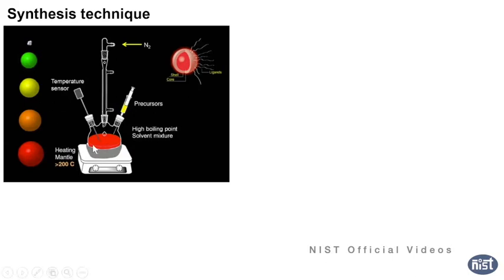And there's a temperature sensor, so you can change the temperature in the solution. Generally we work at high temperature, mainly above 200 degrees, depending on which quantum dot you are making. So you can control the temperature sensor and fix the temperature, and it generally reacts under an inert atmosphere. Mainly you use nitrogen, and you can use argon also. Some materials need argon, but otherwise nitrogen is fine. So you can pass the nitrogen inside the solution.